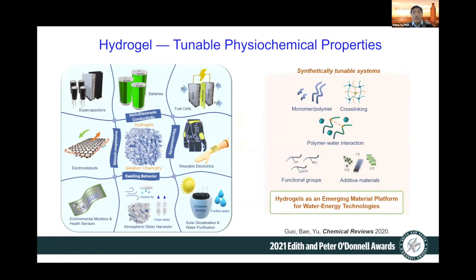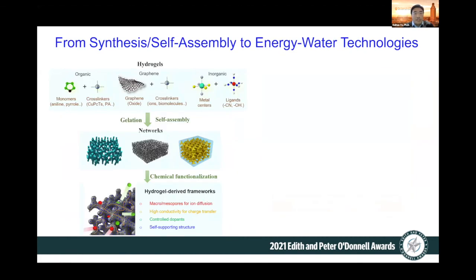Since starting at UT Austin, we have been working to develop a class of highly synthetically tunable nanostructured conducting polymer hydrogels. They are hierarchically porous, structurally tunable in size, morphology, and porosities. The tunable elements for gelation include the basic building blocks, different cross-linking mechanisms, and functional additives. This powerful gelation chemistry endows these hydrogels with very tunable physical-chemical properties. These properties can be integrated into various materials and components, and go beyond biological applications into energy storage, conversion, and sustainable clean water production. Today I'm going to list several examples.